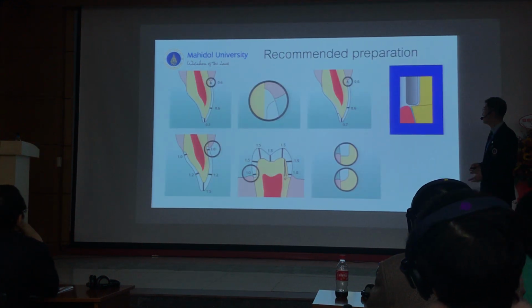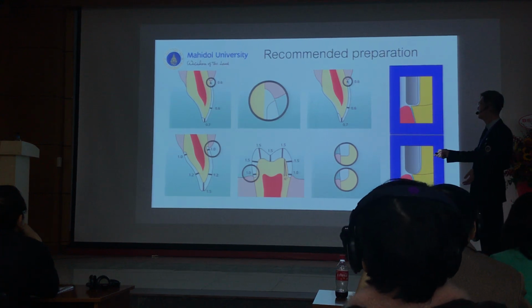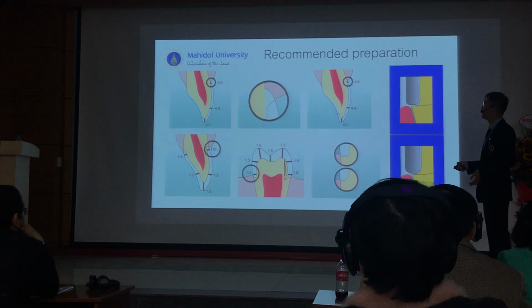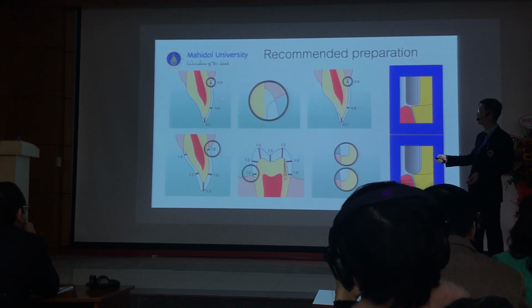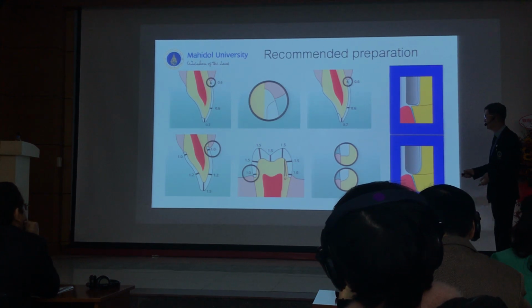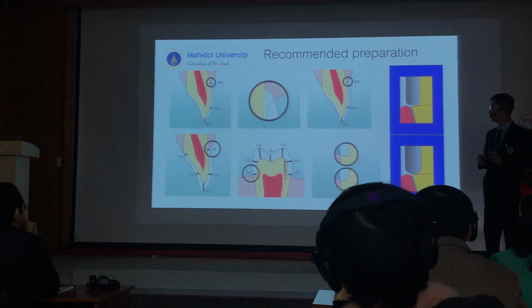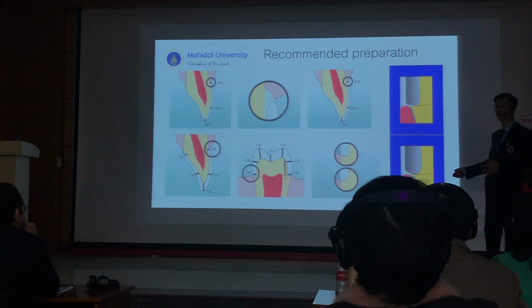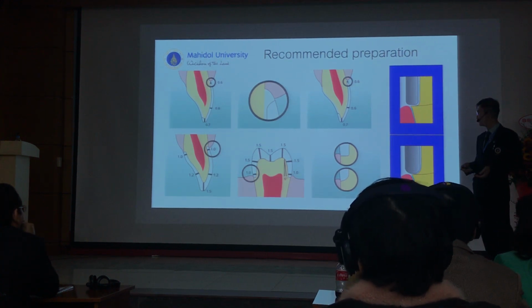And finally, the ferrule preparation of the abutment. You have to be concerned. In the morning session, you can see maybe for the beginner, you don't need to worry because there's no stay over here. Okay, just at the radio, maybe you can make it 0.6, 0.7. But for the crown, at least, even zirconia or e.max or plastic, you must do it around 1 millimeter. Otherwise, it's going to be fractured, very shortly or in the long term.